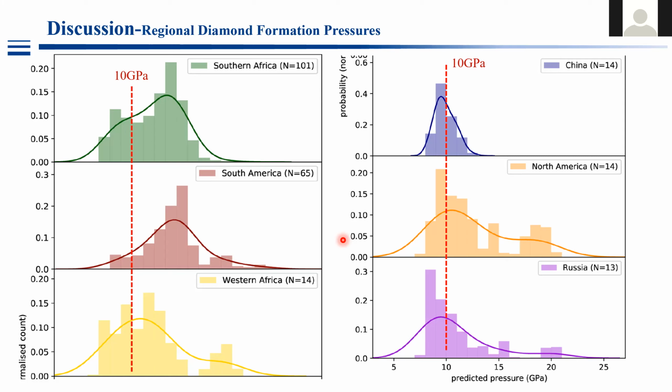Yeah, because for Thompson himself, in his 2016 paper in Nature, that's the highlight of his PhD work, he used carbonated peridotite and put it at high pressure to look at the melting temperature. And it shows that up to 25 GPa, the carbonated peridotite has a very low melting temperature. I forgot the exact temperature, maybe 1200 degrees C, something like that.